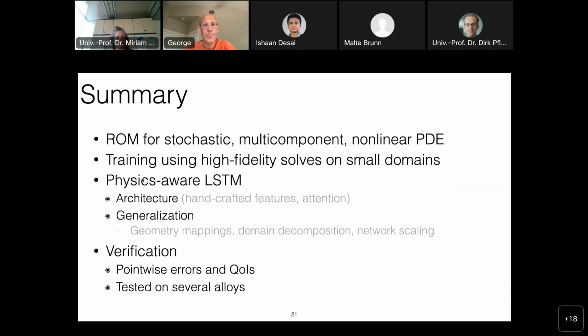So in 2D, I described this reduced order model for stochastic multi-component nonlinear PDEs. It has several features. It has the manual handcrafted feature to reduce the dimension. Then we have a physics-aware LSTM which we use in order to train on 8 grains, and then we're using physics-based extensions to map it to a large number of grains and the melt pool geometry, and present the results on predicting the quantity of interest.